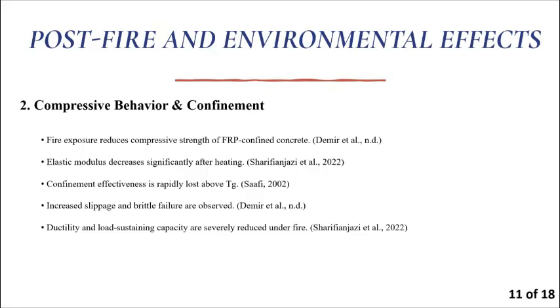For now, I will discuss the compressive behavior and confinement of FRP reinforced concrete under fire exposure. Actually, FRP is often used to confine concrete columns. This confinement increases compressive strength and improves ductility at normal temperature. However, under fire exposure, this benefit is significantly reduced. When the temperature rises and exceeds the glass transition temperature, the resin inside the FRP softens. As a result, these confinement effects become weaker. This leads to a reduction in compressive strength and elastic modulus of the concrete.